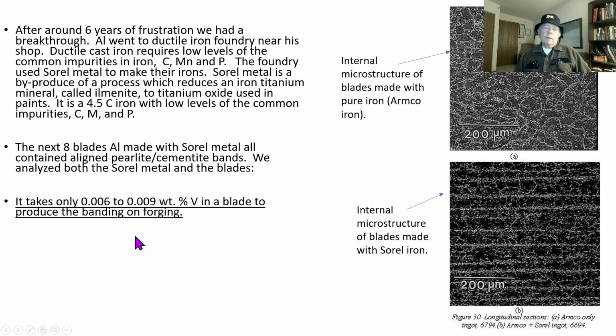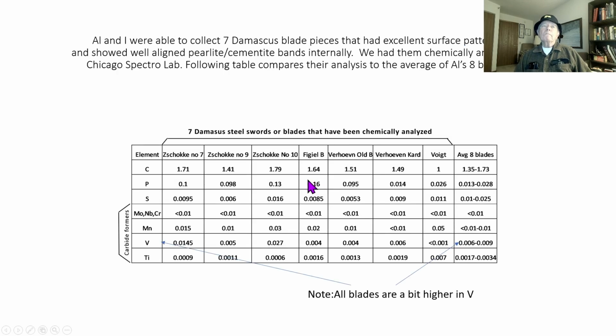On the next slide, I'm going to show you that the average composition of vanadium in the blades was measured to be a minuscule value between 0.009 and 0.006. I could hardly believe it, that such a small amount could cause such a large effect. But it does.